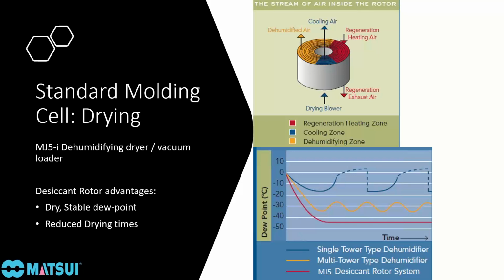A concern is whenever the desiccant beds rotate or switch, there's a fluctuation in the dew point. The dew point level will spike before dropping again. And the issue is all the material, all the plastic resin as it goes through the drying hopper doesn't have consistent low dew point air going over it. It has a fluctuating dew point going over it.